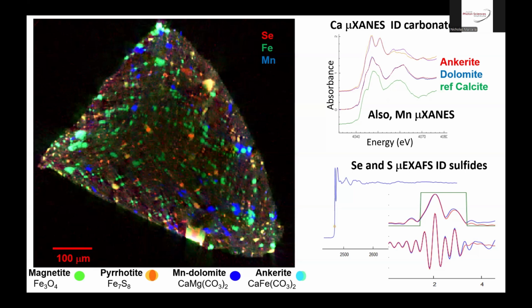We also used selenium and sulfur XAFS to identify the sulfide minerals that are present, mostly pyrrhotite. And selenium is a chemical proxy for sulfur in most natural systems, so you can use either one. And the selenium was easier to access inside the sample with hard X-rays. So that's a good pairing.